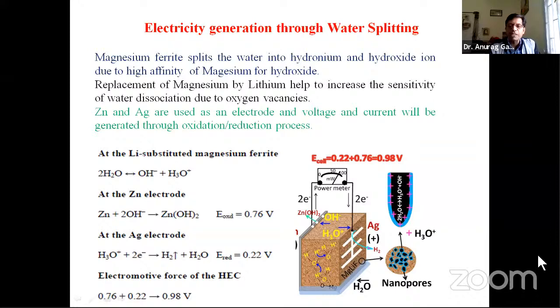So this is the mechanism. I will tell you how this works. We have this lithium-doped magnesium ferrite material, with zinc on one side and a silver contact on the other side. What is the mechanism? Firstly, this lithium-substituted magnesium ferrite material splits the water, 2H2O, into OH minus ions plus H3O hydronium ions. Then what happens? These OH minus ions move towards the zinc electrode.